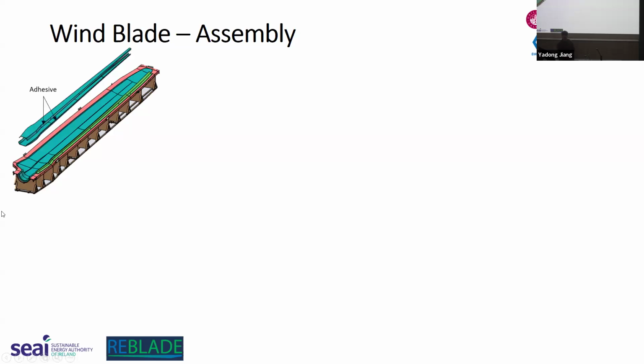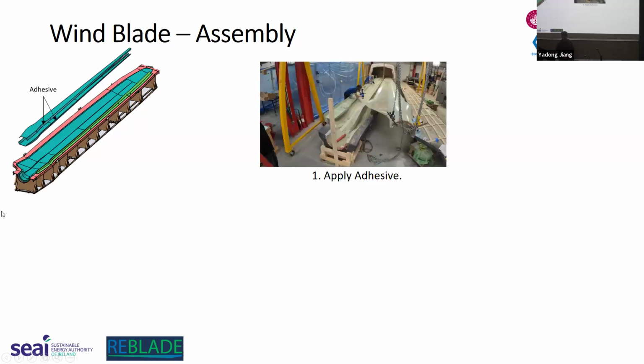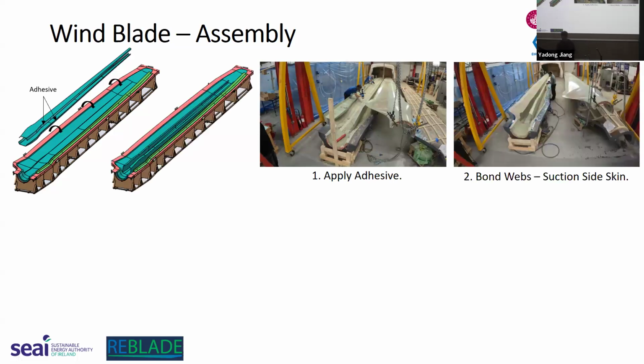So we apply adhesive to the two web flanges. And so you can see here in that image that's just popped up, myself and my colleague Tommy were applying adhesive along the flanges using a pneumatic applicator. So we just put the adhesive cartridges into the gun, and then there's an airline hooked up, and it squeezes or pushes the adhesive out onto the flanges. Then you can see the arrows. Then we just flip the blades into position.